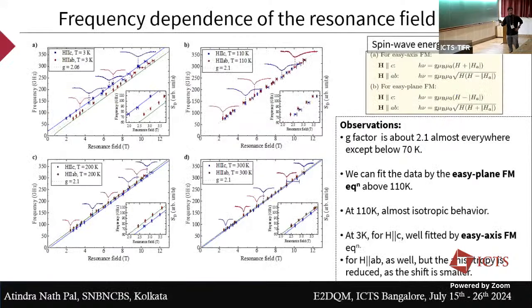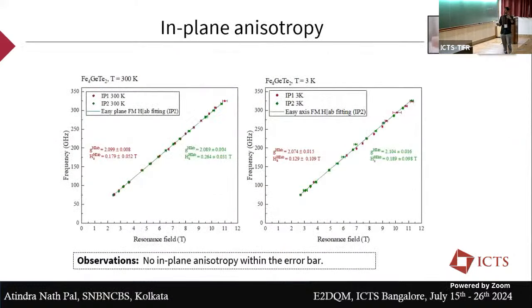The first thing you can do is determine the g factor from the frequency dependence. The g factor remains almost constant in this case, close to 2.1. However, at low temperature there is a slight deviation, 2.06, and you can also see a deviation if you plot the frequency dependence data for H parallel to C and H parallel to AB. I'll discuss the deviation later, but more or less the g factor is 2.1 plus or minus 0.01 in this range.